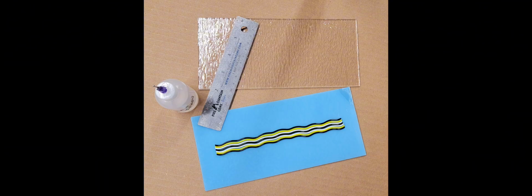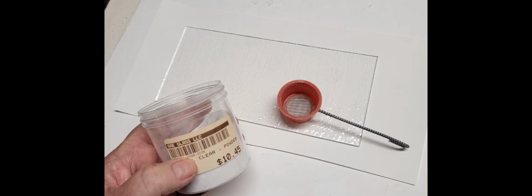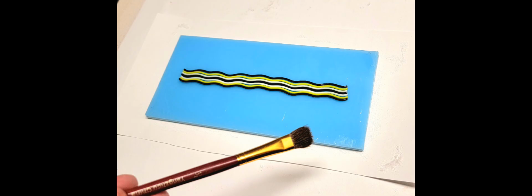The blue glass and attached stringers were then laid on a clear glass that was sprinkled with clear powder for bubble control. This mist of powder allows routes for bubbles to escape from between the layers during firing. For bigger pieces, I would add a bubble squeeze segment as well. After stacking the blue glass onto the powdered clear glass, all residual powder on the surrounding paper was brushed away from the glass to prevent little spikes. Missed spikes found after firing can be smoothed with diamond pads or fine sandpaper. Brush the powder away from the glass stack, but do not brush the powder onto any unwashed kiln surface. The piece was fired to this low fuse temp to preserve some of the stringer texture.